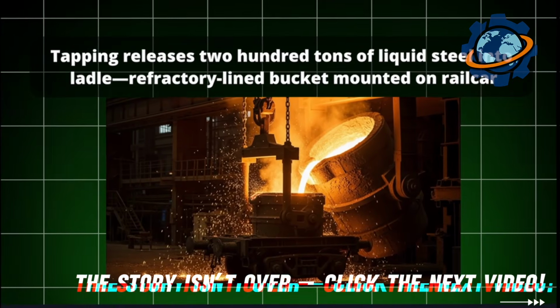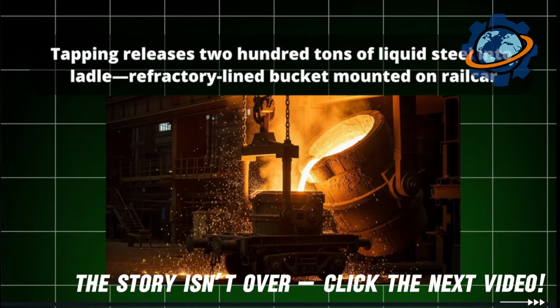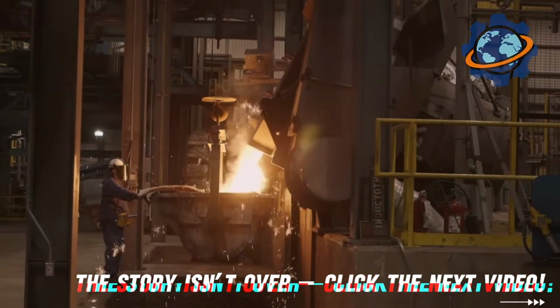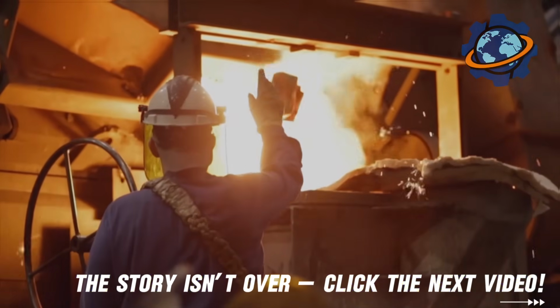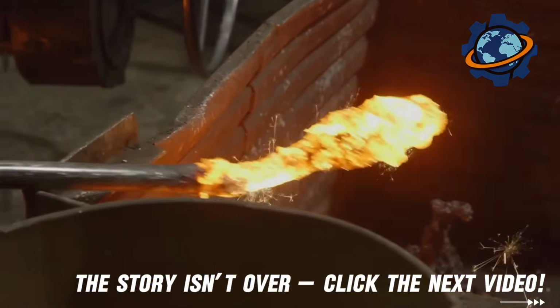Tapping releases 200 tons of liquid steel into ladle, refractory-lined bucket mounted on railcar. The pour takes 8 minutes, continuous stream of glowing metal creating updrafts lifting dust into air. Workers monitor from shielded stations, faces illuminated by orange glow. The steel, now 3,050 degrees, travels to continuous caster where transformation into solid bar begins.